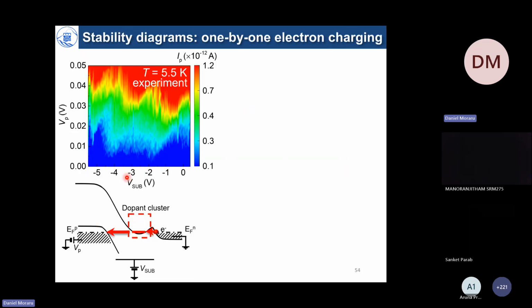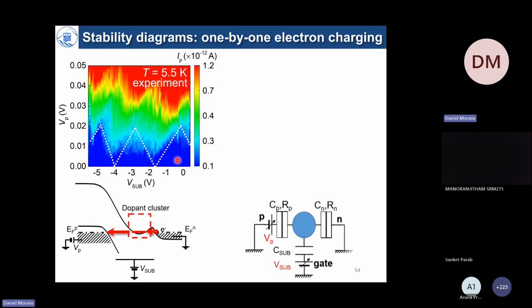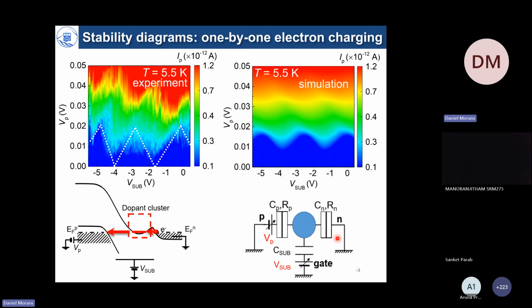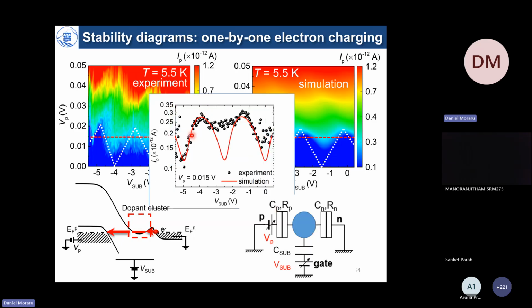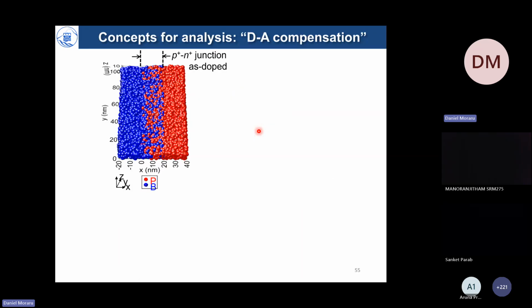So we measured the effect of V sub, and although the noise is quite high, we could observe in this kind of stability diagram, half of it only for positive VP, the modulations of current as shown here. And these modulations can be mimicked by a single electron tunneling circuit. I explained it a little bit earlier. If we tune the parameters to be consistent with what we expect in the experiment, we can simulate at the same temperature similar structures in our equivalent circuit. So that is already some proof. And if you take a line scan here, the experimental data and the simulation data can be made to fit reasonably well, with a few exceptions in a few parts of the device. But for us, that was sufficient evidence that we are dealing with a quantum dot.